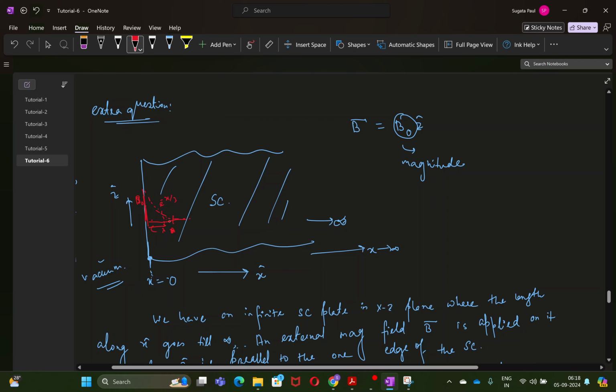Beyond this point the magnetic flux, even if it is present, is so small that we can almost say that deep inside the superconductor the magnetic flux cannot penetrate anymore, because superconductors are perfect diamagnets, so it decays down to 0. So inside, B equal to 0. This effective length scale is called the superconducting penetration depth, and the value is in the order of 10 to 100 nanometers.